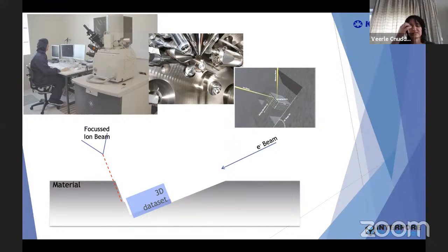By removing and then always taking a picture, you are virtually making a 3D data set. The drawback of this technique is that it's destructive and only works for small samples, small volumes. If you are studying dynamic processes, you may not want to destroy your material, and you're looking for an option to look inside at high resolution in 3D, non-destructively.